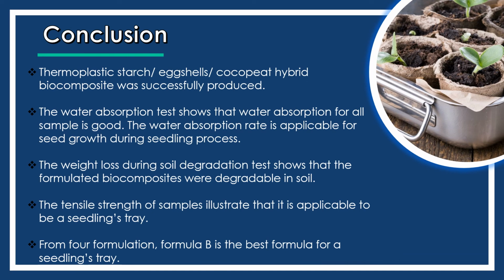For the conclusions, the thermoplastic starch eggshell cocopeat hybrid biocomposite was successfully produced. The water absorption test showed that water absorption for all samples is good and the water absorption rate is applicable for seed growth during the seedling process. The weight loss during the soil degradation test showed that the formulated biocomposite were degradable in soil, and the tensile strength of the sample illustrates that it is applicable to be a seedling tray. And from 4 formulations, formulation B is the best formula for a seedling tray.